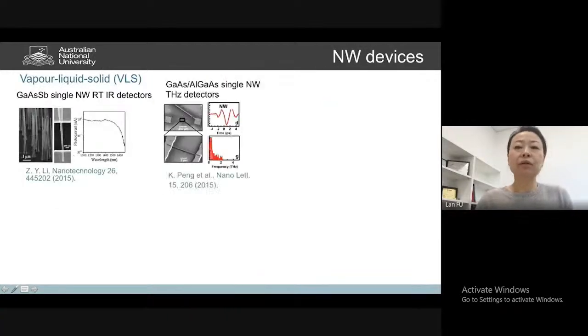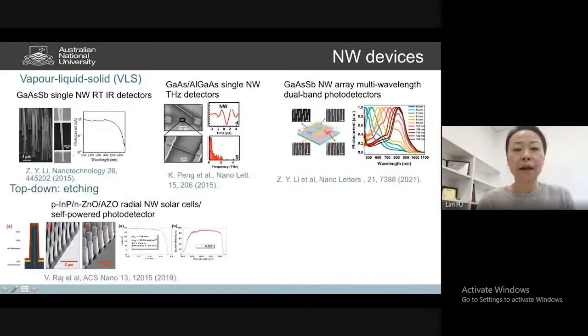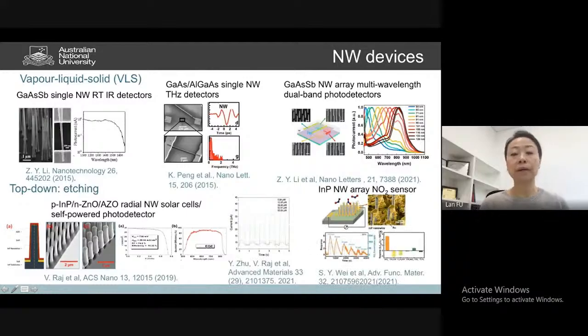In our group, we've demonstrated a lot of single nanowire devices in the past, as well as array devices. I wouldn't have time to talk about each one of them. Basically, what I want to show you is that there are a lot of possibilities for exploring the unique properties of these nanostructures. You can see that by changing the materials as well as the characterization technique, we have demonstrated that single gallium arsenide antimonide nanowires, because they have a lower band gap, can achieve photodetection at telecommunication wavelengths, which is 1.3 and 1.55 micron, at room temperature.